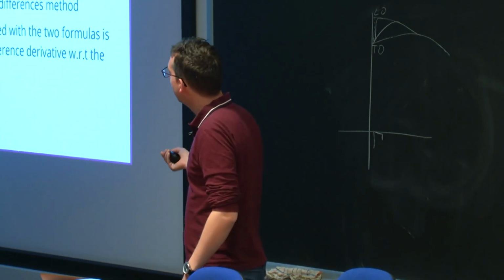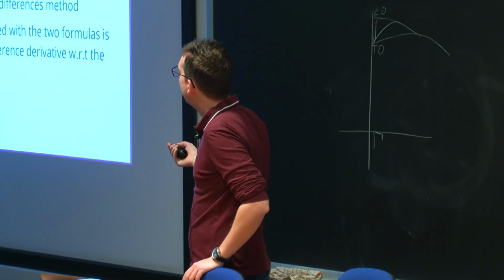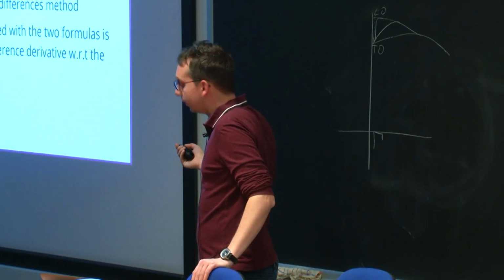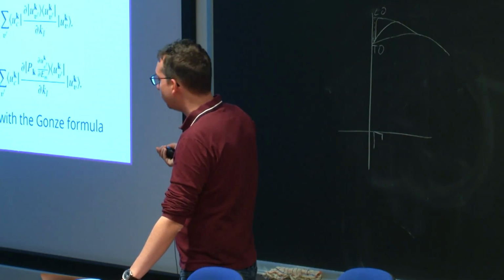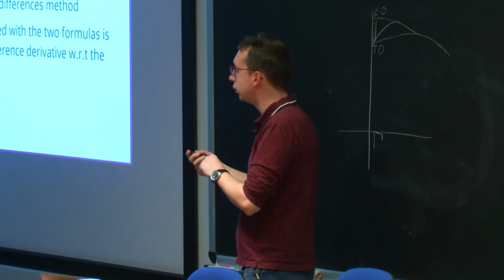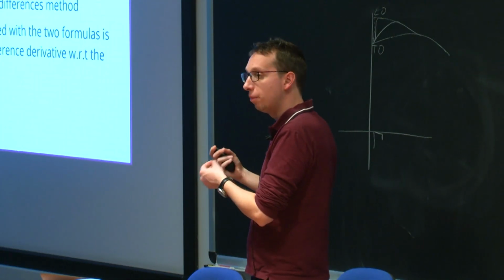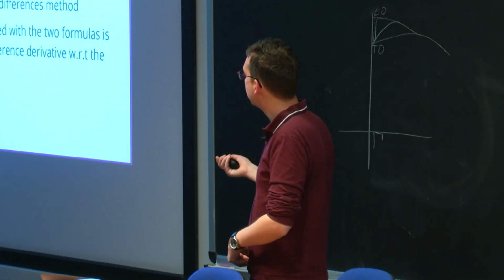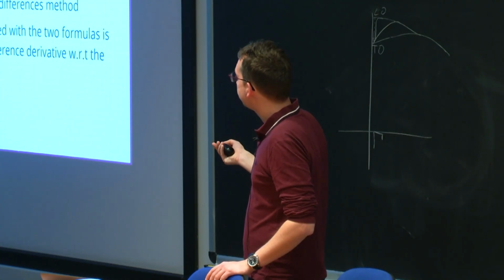So one critical component of the calculation in practice is to check the convergence with the k-points grid, a bit because of this derivative here. Doing a derivative of a wave function with respect to the wave vector is a bit tricky because there is an arbitrary phase associated with each k-point which can appear. You can get rid of that with some method, but still you have to be a bit careful.